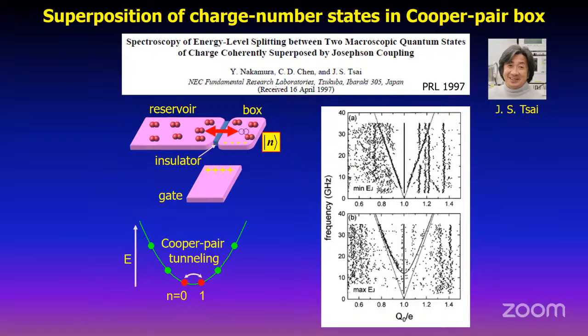And at NEC in Japan, our team worked on a similar device, but using spectroscopy to study not only the ground state, but also the excited state. So here, again, in a similar device, we create a superposition. And then because of the superposition, we have a bonding and anti-bonding state between the two charge number states that we observe in the microwave spectroscopy, to see this opening of the anti-crossing of these two states as a function of the gate voltage. So this is the evidence of macroscopic quantum coherence between two different charge number states in an electrical circuit.